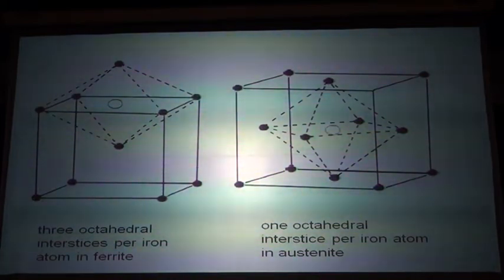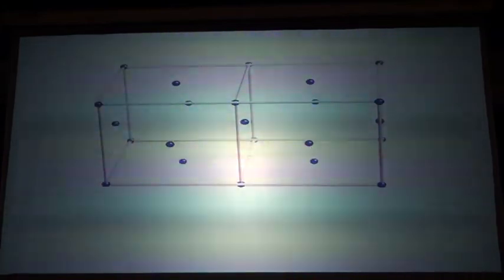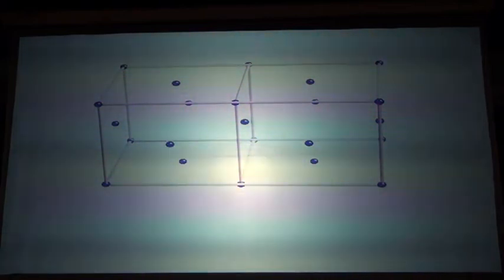Its strain is asymmetrical. So I got to thinking and I said, look, we are calculating the equilibrium between cubic ferrite and cubic austenite. Supposing that the ferrite was tetragonal, you know, there was some ordering of the carbon atoms, then how does the iron carbon phase diagram change? So why should the ferrite be tetragonal? Almost every paper that has been published will analyze the X-ray data on bainitic ferrite using a cubic lattice. That's exactly what we ourselves have done for many, many years.